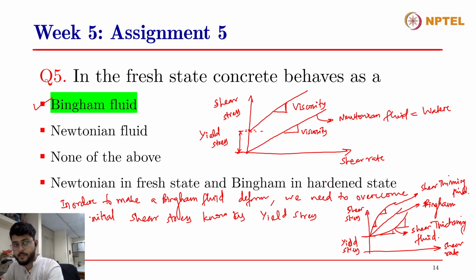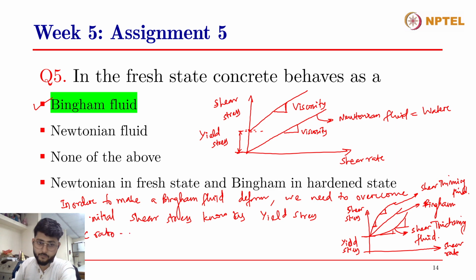Even though we are discussing in this question that fresh state concrete behaves as a Bingham fluid, but not always so. I want to emphasize here that not always does concrete conform with a Bingham behavior. It sometimes shows shear thickening fluid behavior also, as in the case of low water to cement ratio. At low water to cement ratio, concrete sometimes, depending on the mixtures, like the powder content in the mix, or if you have added any fine materials like pozzolanic or supplementary cementitious materials in the mix, then depending on the mixture design as well, not just because of the water to cement ratio, but depending on the other constituents in the mix as well, concrete might show a shear thickening behavior.